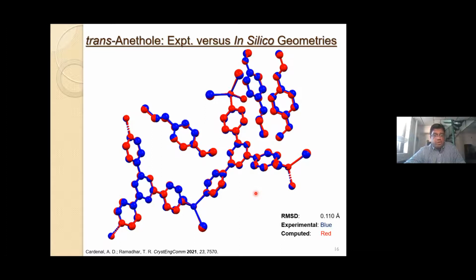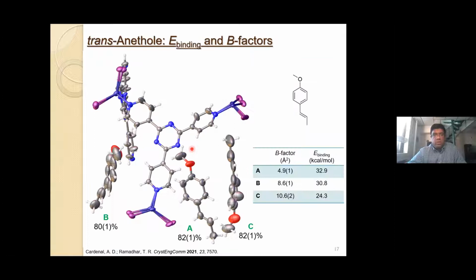And it also helps to reinforce the validity of the crystalline sponge method because we were able to model the guest molecules correctly, especially since you're dealing with diffuse electron density. You feel like, is this method really real or not? And the good agreement between experimental and computed structures indicates that this technique really does work. So it provides further validation overall for the crystalline sponge method.